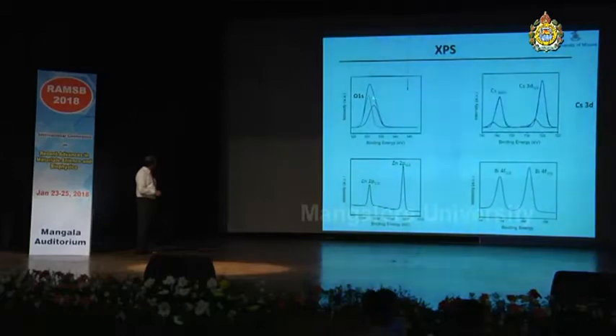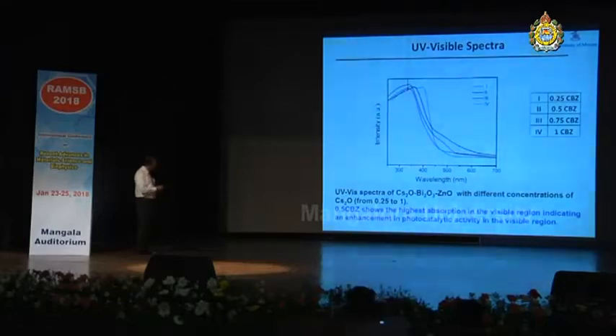and we then subjected the same composite to the XPS study, and you can see the binding energy peaks for cesium, oxygen, zinc, and bismuth in these composites. And the UV visible spectral image is shown, and in fact we get the best result for the 0.5 CBZ, corresponding to cesium oxide, bismuth oxide and zinc oxide.